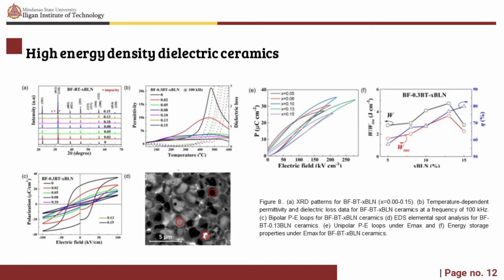which is less than or equal to 0.02, as can be seen in figure 8c, were not regarded suitable for the energy storage application due to their low BDS, about 120 kilovolts per centimeter, and substantial energy loss. Compositions where x is greater than or equal to 0.05 and less than 0.15, with a strong core-shell contrast, have higher potential energy storage and are being investigated further.